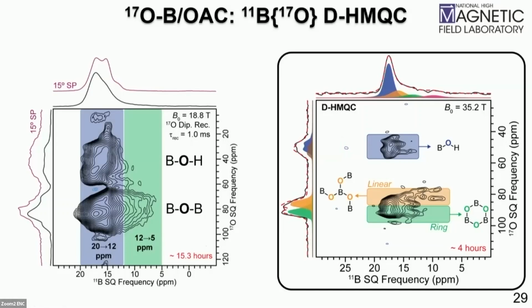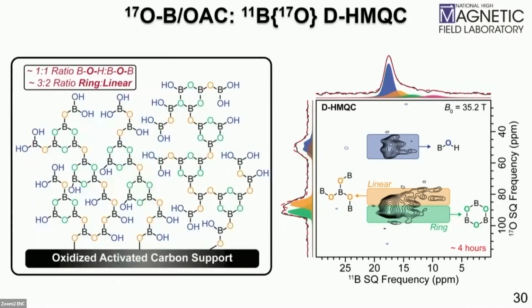And we are looking at a surface here of only about 20% enriched oxygen. So this is quite impressive. And what you can see, we get very good resolution, and we can actually resolve the linear from ring type bridging oxygen atoms in this HMQC. So now we can really start to build a complete picture of molecular structure because we know that this is extremely hydroxyl dense and there are a lot of ring type and linear borate species.